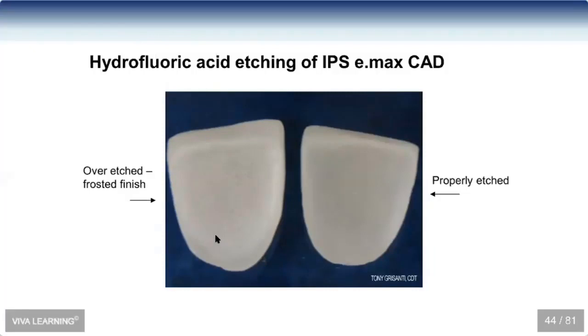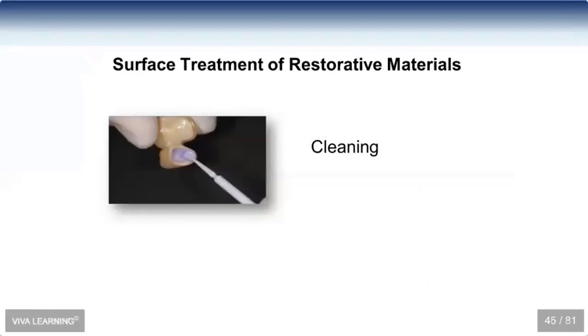So why would a lab tech over etch this? Well, not intentionally, but when I witnessed it at Glidewell, they'd be etching a bunch at the same time. And by the time they finished the last one and glanced down at their phone at an Instagram notification they got, and they got back to the first one to rinse it out, it had been 60 seconds. It's more of that and not an intentional over etching, but you actually lose bond strength and it weakens the material as well. We don't want to etch that much glass from here. Hydrofluoric acid will just keep going. It doesn't know when to stop, and that's why it needs to be rinsed out after 20 seconds.